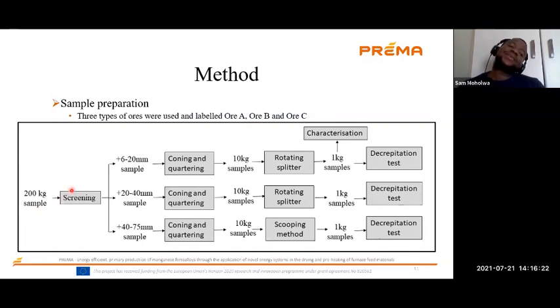Approximately 200 kg of each ore was sourced. This 200 kg was taken through screening to get these three size ranges. These three size ranges were then taken for coning and quartering so that we can get 10 kg samples, which will then be taken to a rotating splitter so that we can further split them into 1 kg samples, which we are going to use for the decrepitation test, and take some for the characterization.